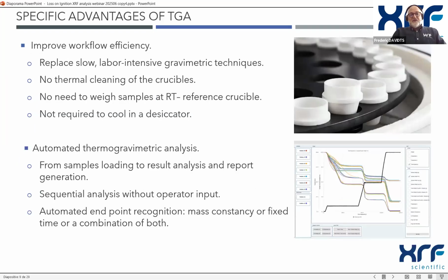So the specific advantages of the automated thermogravimetric analyzer: we, of course, improve the workflow efficiency, replacing the slow, labor-intensive gravimetric technique. We don't need to do the thermal cleaning of the crucibles. We don't need to wait for the samples to reach room temperature after each step. And that's because we have a reference crucible inside that deducts the weight variation we can have from the crucible. So no need to do a thermal cleaning, and no need to reweigh the sample at room temperature.